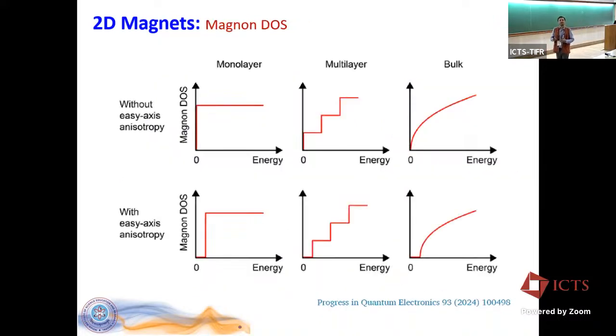Now, magnetism in 2D systems may also be looked at from a different perspective, which is through the magnon picture, where one can look at the magnon density of states and see whether or not long-range ordering will be allowed. Here are two different scenarios. If there is no easy-axis anisotropy, there is no gap in the magnon states, and therefore long-range ordering is not favored. But when there is an easy-axis anisotropy, a gap pops up, and there one may have long-range ordering or quasi-long-range ordering.